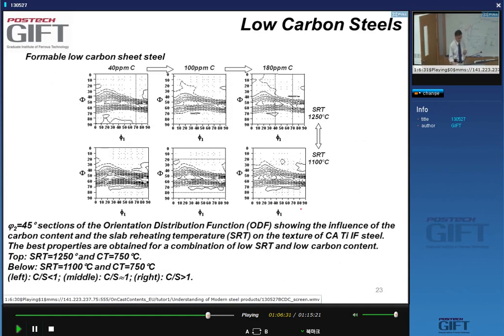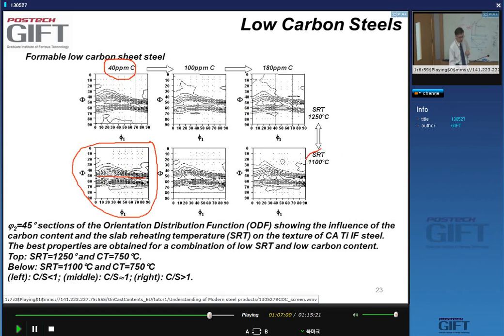Yes, and you can also see this goes very far. This effect of the slab reheating temperature goes very fast. You can see that if you look at the ODFs here, this ODF gives me the best gamma fiber, very intense gamma fiber. And it corresponds to low carbon content and a low slab reheating temperature.